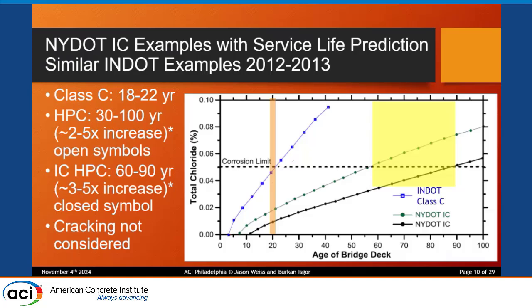You can use this information, as I mentioned. These are actually done with a full life cycle model using ionic transport, using Stadium or a similar type of approach. The basic issue here is, if you use that conventional concrete, it's going to crack at around 18 to 22 years, or it's going to start to corrode at around 18 to 22 years. But this is only where the concrete doesn't crack.